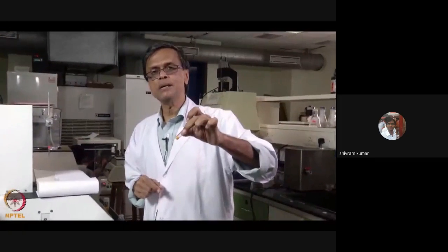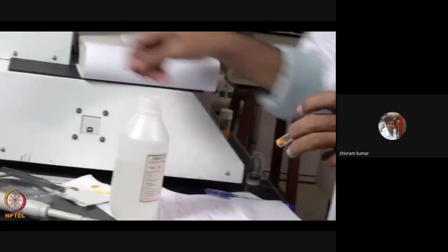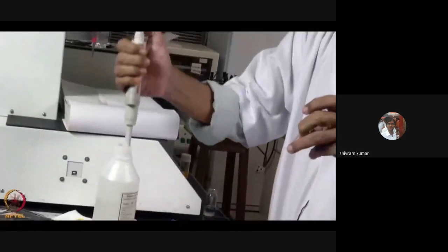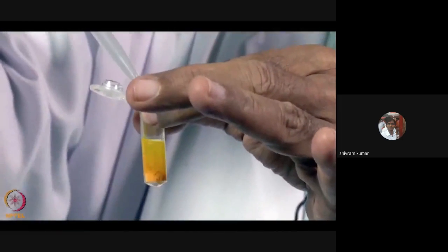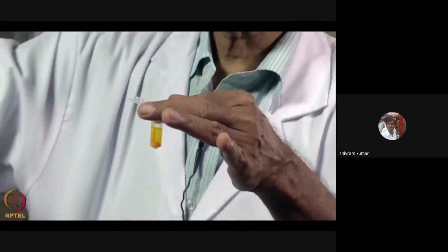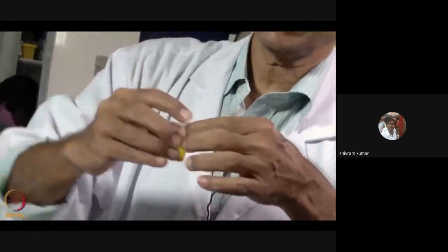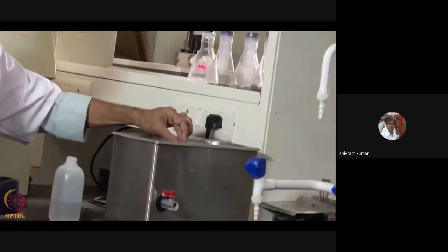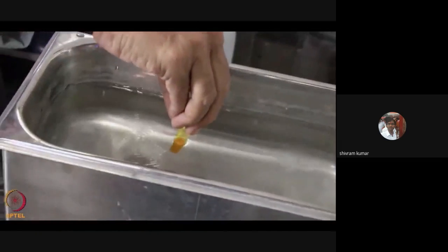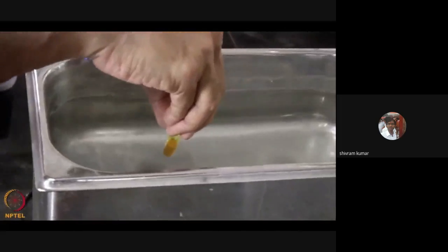We take 200 milligrams of curcumin. Curcumin is not water soluble, so we need to dissolve it in ethanol. So we add 1 ml of ethanol. Now we need to mix it thoroughly using a water bath sonication. Curcumin has to be dissolved and dispersed in ethanol, so we use a water bath sonicator.